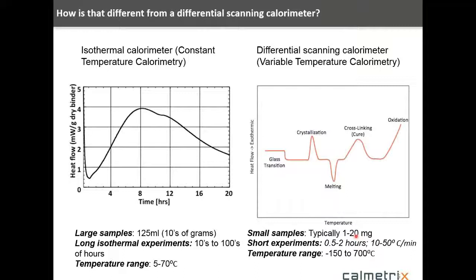As opposed to DSCs, which use very small samples, typically in the order of 1 to 20 milligrams, so you're talking an order or two of difference in sample mass. They're very short experiments because the mass of the sample is small and the system is small. We ramp temperature in these devices typically. They can change temperature very rapidly. They can run isothermally, but normally they're running in a temperature ramp mode, say 10 to 50 degrees C per minute, so the time frames are very short, and the temperature range is usually pretty broad from minus 150 to greater than 700 degrees C.